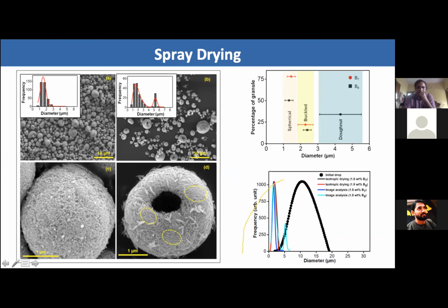On the right are the droplets that are being dried with higher aspect ratio ellipsoids, and it turns out that depending upon the aspect ratio of the particles, you either get more spherical granules, or granules that are deformed, or granules that are in the shape of a donut, depending upon the aspect ratio of the particles in the fluid. So if you're interested to know more about this, you can drop me an email. I'll be happy to discuss this a little bit.